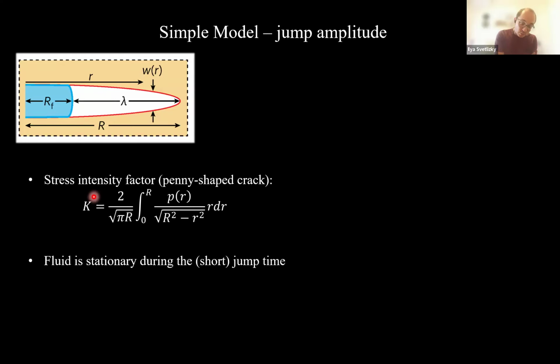So what we decided to do is basically to ignore the fluid. The justification is that the jump of the crack is so fast that we assume the fluid front is stationary and doesn't move during the jump. So we only need to specify the pressure profile that the fluid applies on the crack faces. If the flow is very viscous, you would naively assume the pressure profile has to be linear. If the viscosity is very low, the pressure can be almost constant. You take these two limits, and it doesn't make any big difference.